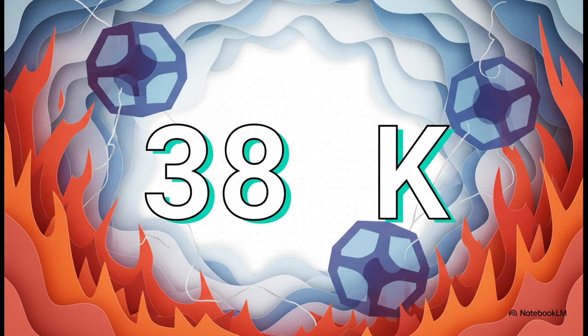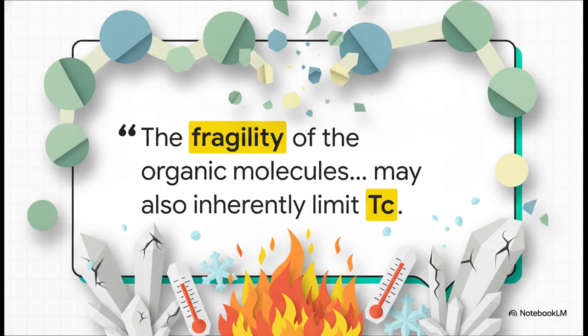And reaching even that 38 Kelvin still requires extreme pressure. Our source material hits on a pretty harsh reality with this quote. The fragility of the organic molecules and the crystal structures may also inherently limit TC. We're currently battling what physicists call the TC problem. Basically, organic structures are relatively soft, they're easily disrupted. Finding a way to push these temperatures higher so we can avoid the need for incredibly expensive, extreme liquid helium cooling remains one of the absolute greatest hurdles in condensed matter physics today.